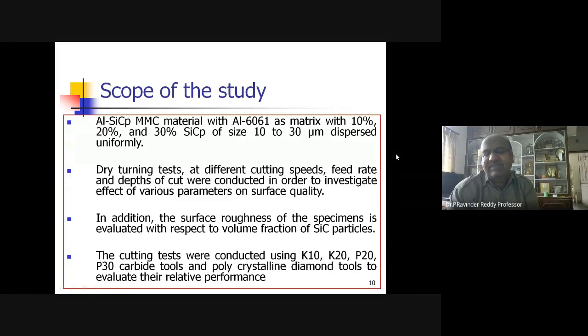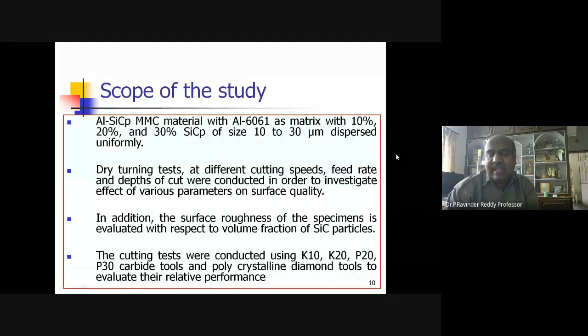In addition, the surface roughness of the specimens is evaluated with respect to the volume fraction of silicon carbide particulates. The cutting tests were conducted using K10, K20, P20, P30 carbide tools and polycrystalline diamond tools to evaluate their relative performance. By comparing all these, we can measure the tool wear, the temperature, the thermal stresses and distortion, and we can conclude which is going to be the best material for the cutting operation, under what conditions the tool wear is less, and what rake angle it is.